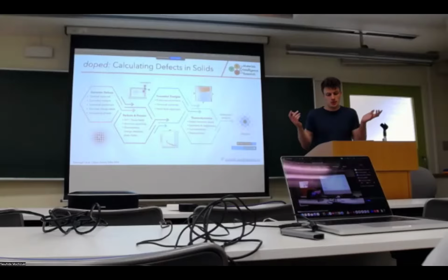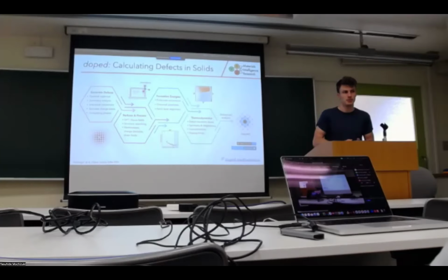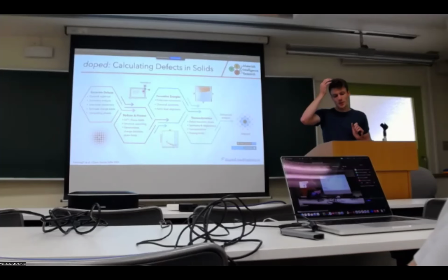This was the assumed hypothesis for about 10 years until some theorists did calculations where they pushed the donor atom to a different site in the material, and found that actually it can have this low-energy reconstruction and become an acceptor-type dopant. So this was one of the first cases of really seeing that metastability at defects can be experimentally verified. There have been some other cases, but I've probably been talking too much. That's okay.